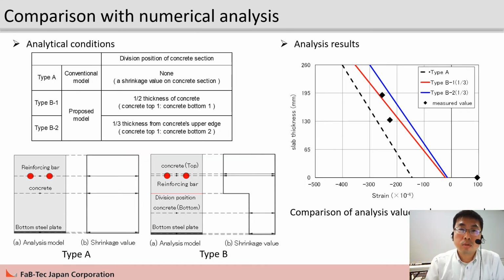This table shows the specifications of the analysis model. Also, the conventional model type A and proposed model type B are shown in figures. This figure compares the analytical and experimental results. Proposed models type B1 and type B2 show that the drying shrinkage value at the concrete bottom is reduced to 1/3 of the top values.